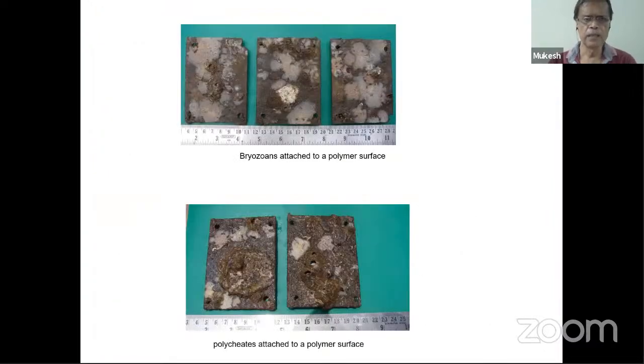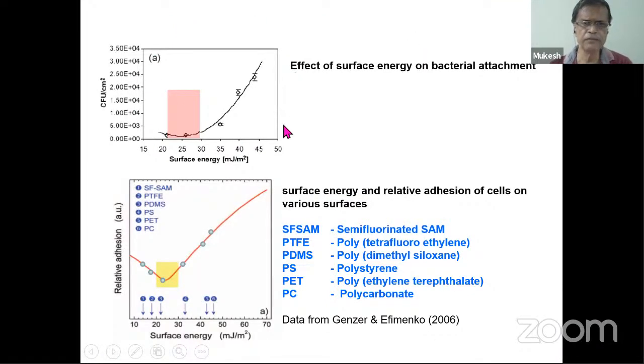One important study which was done is called the Baier curve, the surface energy versus the amount of biofouling. There is an optimum surface energy where the fouling is very, very low. The design of materials for the shipping industry is generally based on this graph. Materials used in the shipping industry should have this surface energy so that the amount of biofouling is the lowest. If you have higher surface energy, you are going to have high CFU. If you have very, very low surface energy, again you are going to have high biofouling. This is called the Baier curve.